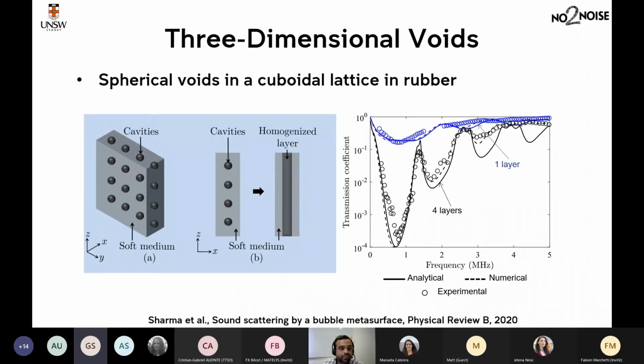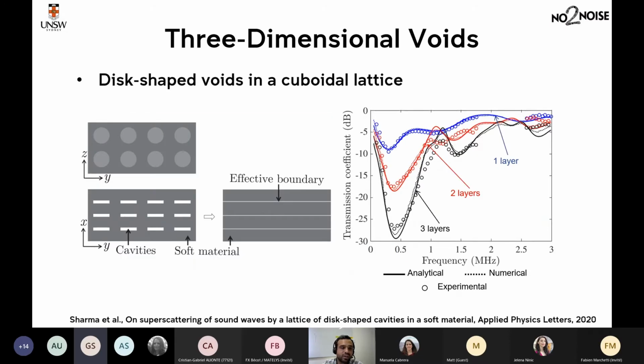For example, here we have spherical inclusions, spherical voids, I would say, cavities, and they're arranged periodically in a soft medium. And here again, I'm presenting results for 1 and 4 layers. You can see that this is the monopole resonance frequency, and at monopole resonance, you see that there is really low sound transmission through your structure. You can model different shapes. Doing it analytically is actually fun. Doing it numerically is easy. You can simply change the shape of your inclusions.